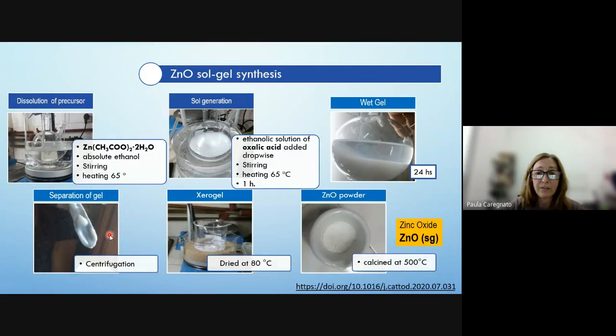In the Sol-Gel synthesis, the precursor is zinc acetate, and the sol is generated by adding an ethanolic solution of oxalic acid with stirring and heating for an hour. The wet gel is generated after 24 hours, and then the gel is separated by centrifugation. It is dried and finally calcined at 500 °C. This material is named zinc oxide Sol-Gel.